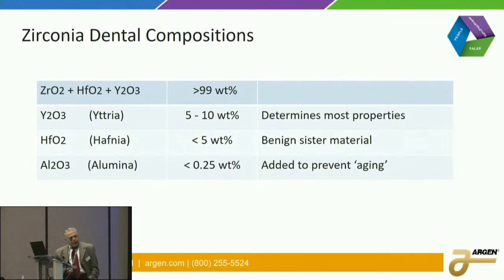Now, alumina was added initially to prevent something called aging, and this is where the zirconia actually falls apart. This happened when zirconia was used in hip joints. The water in the bodily fluids was actually getting forced into the grain boundaries of the zirconia, and that just broke it apart. By putting a little bit of alumina in there, they found that they could stop it from happening, and that made it opaque. And that's why the initial materials like zirconia were opaque. And today, even if you use a high-strength material that you're going to bake porcelain on, those materials are opaque because of this amount of alumina.